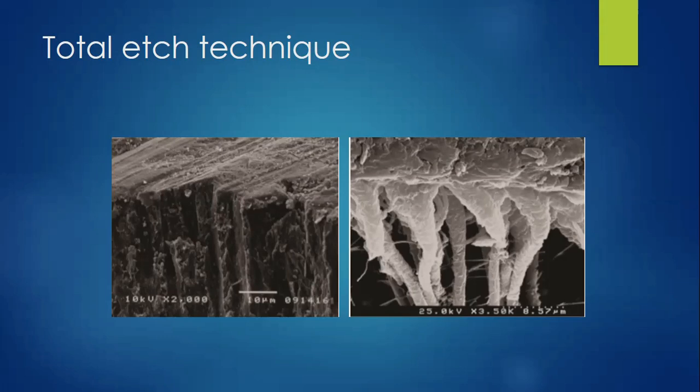So these proteoglycans will act as filters for molecules with high molecular weight, allowing many small molecules like HEMA to impregnate at a deeper level. So our superficial layer will be more hydrophobic, and the lower one will be more hydrophilic due to interdiffusion of low molecular weight and hydrophilic particles like HEMA, which will further lead to deterioration of this layer. This hydrated network connects the resin tag to the base of the hybrid layer. In between there are water molecules, and because they are connected with each other, they are connected to the base of the hybrid layer through their lateral ramifications.